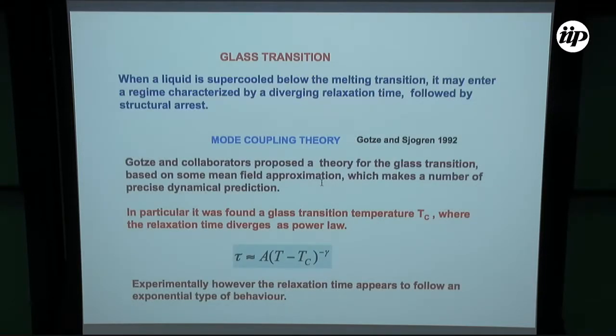So let me first say a few words on the glass transition, in particular on RFOT, the random first-order transition. As you know, when a liquid is supercooled below the melting transition, it may enter a regime which is characterized by very slow dynamics with diverging relaxation time, which is followed by structural arrest. One of the first theories, proposed by Götze and collaborators, was the mode coupling theory, a theory for the glass transition based on some approximation that nowadays we understand is some sort of mean field approximation. This mode coupling theory makes a number of precise dynamical predictions, and in particular, it finds a glass transition temperature, Tc, where the relaxation time diverges as a power law.